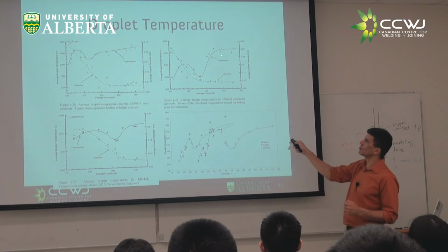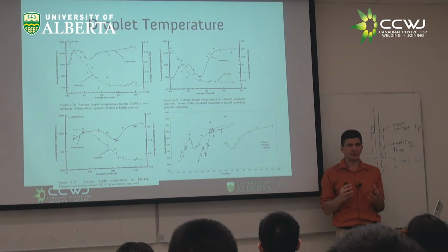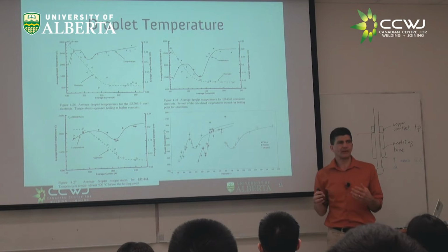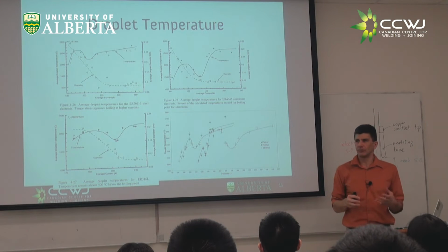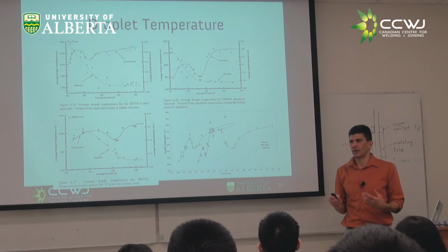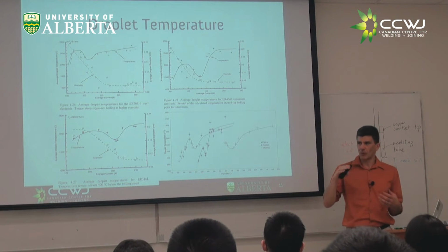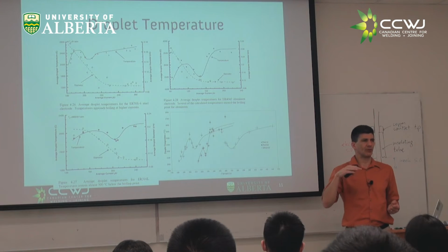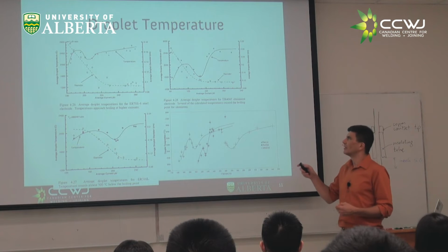Right? And this saturation is at a temperature close to the boiling temperature of your alloy, or boiling temperature of your components. So for example, if you have pure aluminum, it's high. So if they're 2500 C. But if you have aluminum with magnesium, magnesium has a lower boiling point, and it lowers the boiling point of the droplet. Right? It's a very, very interesting thing.